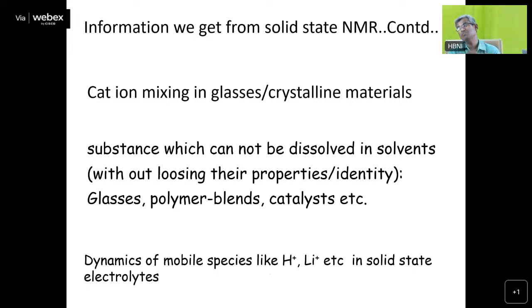This information we cannot get by XRD, X-ray diffraction. NMR is the only technique that can give information regarding the mixing of cations in glasses. Because first of all, it's a low Z element. And second, you cannot even use XPS, X-ray photoelectron spectroscopy, because the atomic number is low, so you may not be able to get good quality X-ray photoelectrons from this. So with the help of boron NMR, we can get beautiful information regarding the cation mixing, particularly the boron structural units present and how the boron structural units are mixed with the silicon structural units in glasses.